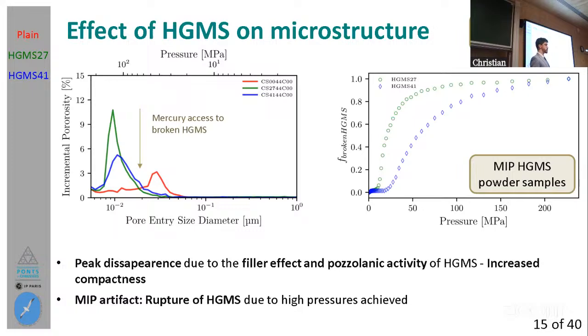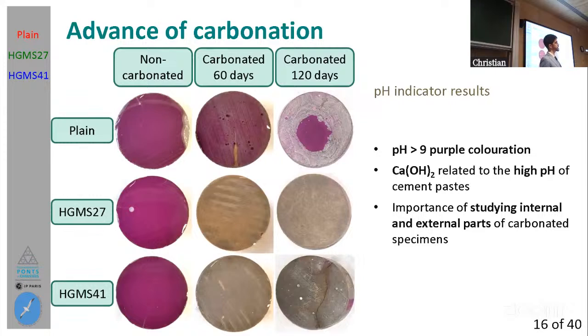Having understood that, I want to focus now on the carbonation, and for doing that, I first show you some results on the advance of the carbonation. This was done with pH indicator, and there you will see the results for a water to solid ratio of 0.44. This first column is the non-carbonated samples, or the cross-section of them. Then we have the second column for specimens carbonated for 60 days, and then the third column for carbonated for 120. The first row is plain cement paste, then the second with the green one, HGMS27, and the third one with the blue one, HGMS41.